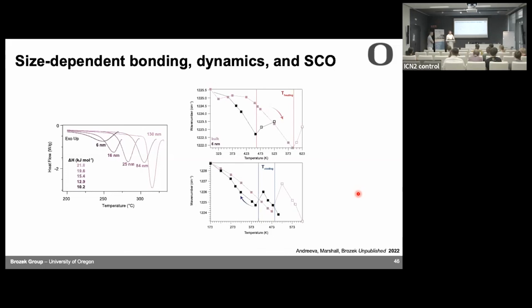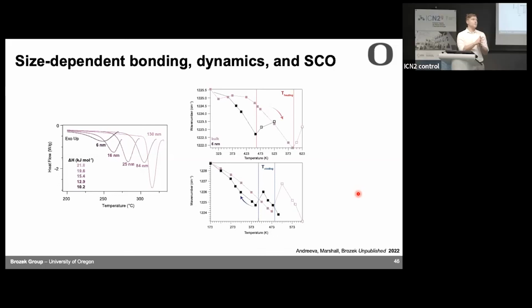Yeah, it's a great question. When I had that slide of why do we care about dynamic bonding, I think it's because this is how MOFs grow. The reason we can get these big, beautiful crystals is because the bonding is so dynamic. So I think you need the high solvothermal conditions, one, so you decompose your DMF and make a little bit of the base, but also because you're encouraging that reversibility. Wouldn't that be favored at 60 degrees where both species are present? Oh, yeah. I don't know. For this particular case, maybe this means that for copper BTC, we could be making the crystals at a lower temperature. That's certainly possible if you have the base in there. Yeah, I don't know.